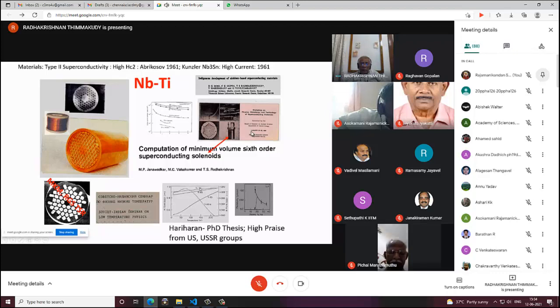physics of the niobium titanium superconductor. For physics, people don't take these complicated alloys. They often take, in order to avoid complication, pure materials. But because of niobium titanium, there's a metallurgical phase instability caused, we believe, there's a lot of evidence, that instability, if present, gives rise to high current superconductors. So we examined niobium titanium for several compositions in that angle, and we found that you can at will